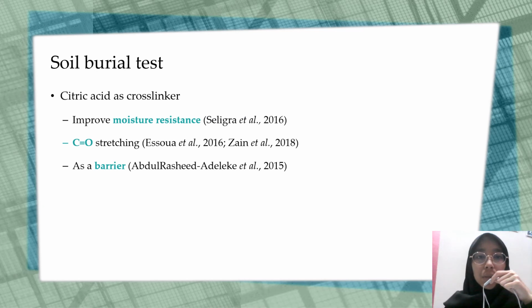Citric acid improves the bioplastic's moisture resistance and slows down microbial activity. The carbonyl stretching also releases free citric acid that slows down fungal action. Moreover, the carbonyl stretching also improves the bioplastic resistance to moisture absorption. Citric acid also acts as a barrier that improves the hydrophobicity of pectin-DES bioplastics.